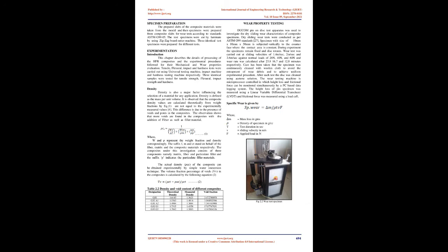Granite powder, a byproduct obtained during the sizing of granite stones by processing granite slabs, has no end use. In the present study, granite powder is used as the reinforcement to the matrix system to prepare composites. Granite powder is massive, hard, and tough, so it has gained widespread use. It is the byproduct material generated by cutting and shaping of building stones in stone cutting plants. The water used for cooling the cutting saw flows out carrying very fine suspended particles as a highly viscous liquid known as stone slurry. The stone slurry was oven-dried, ground and sieved.